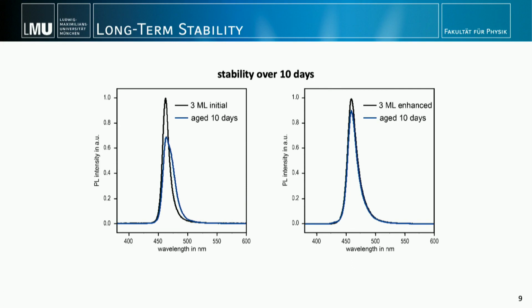Compared to the initial black curve, after 10 days, we have a drop to below 70%. It also gets broader, meaning that the platelets continue to grow, they stack together. But if we do the surface trap repair, which is shown on the right side, after 10 days, we have a slight decrease, but the shape stays the same. And these were not protected, they were just basically standing in the lab for 10 days, so this was a quite good result.